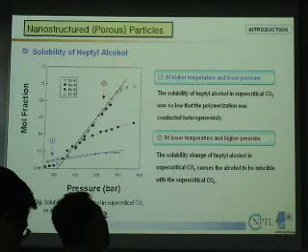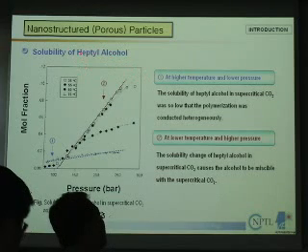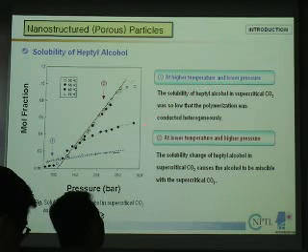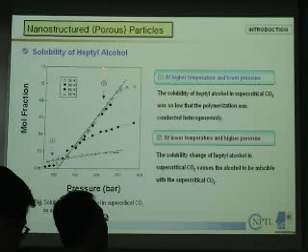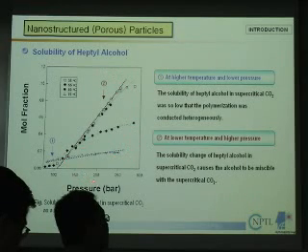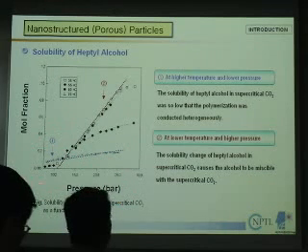That's because the solubility of this heptyl alcohol changes: at higher temperature and low pressure, the solubility of heptyl alcohol in the supercritical fluid is very low. That means you can create the dispersion, a heterogeneous system, in the continuous supercritical fluid in these state conditions.